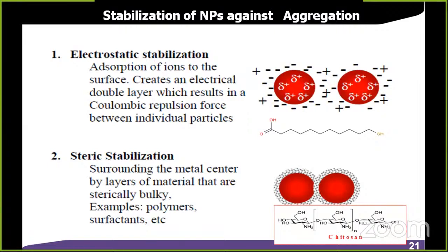If an oxide layer is there, like a silane or mercaptopropionic acid silane, that is a different mechanism. The oxide bond and OH bond can bind. I am talking only about the metal nanoparticles. So this COO minus will be free from the binding in the solution, and that is the negative charge. Here negatively charged, here negative charge, so a negative repulsive force will be there. This is called the electrostatic repulsion.